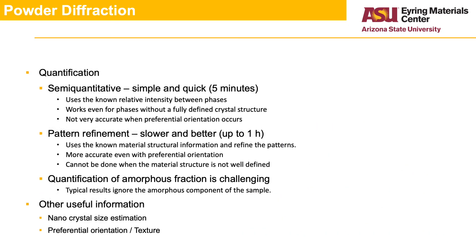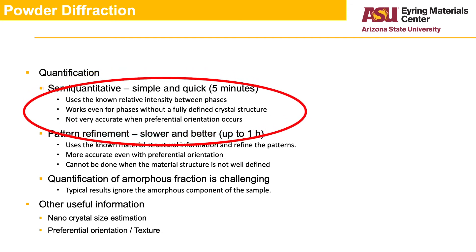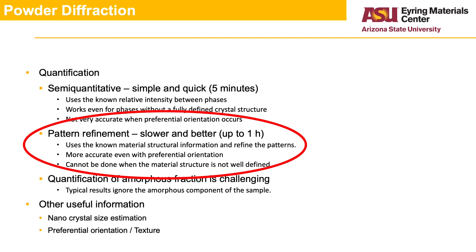It should be pointed out that the quantification can be done in a few different ways depending on the needs. A semi-quantitative analysis, only looking at the relative intensity of the peaks between the different phases, will only take a few minutes. A refinement of the pattern will provide a much more accurate result; however, it requires knowing the full structure of the phases and will take a lot more time.